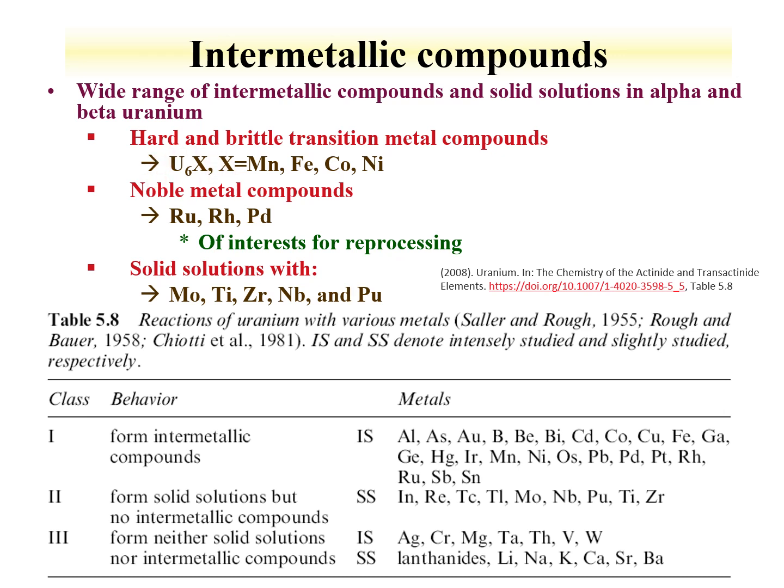These compounds will form. So if you had uranium metal against stainless steel, which can occur in a fast reactor, and you started to have diffusion of the stainless steel into the uranium, you would change that uranium metal to this intermetallic compound. Noble metals can also form intermetallic compounds with uranium. And as we discussed with the alloys, we get something that looks more like solid solutions. Here's a table that says what metals form those compounds. So intermetallics are formed with all these metals.